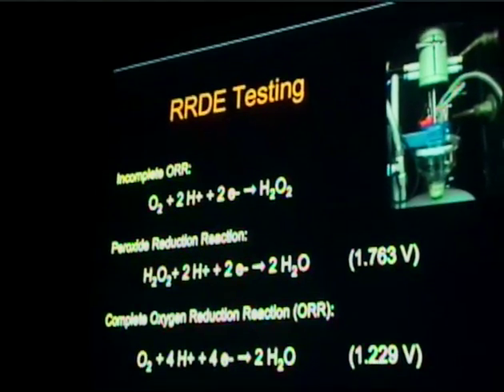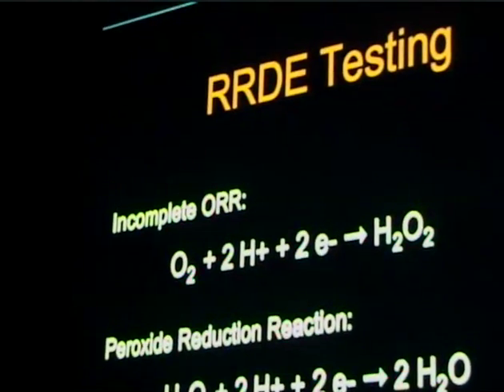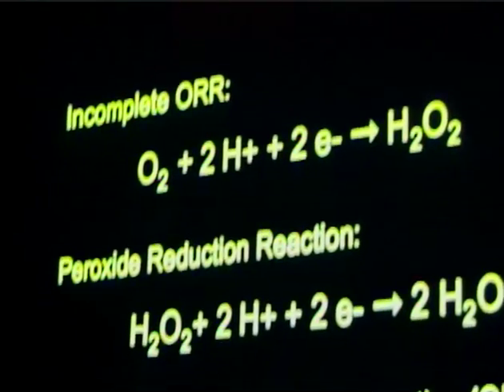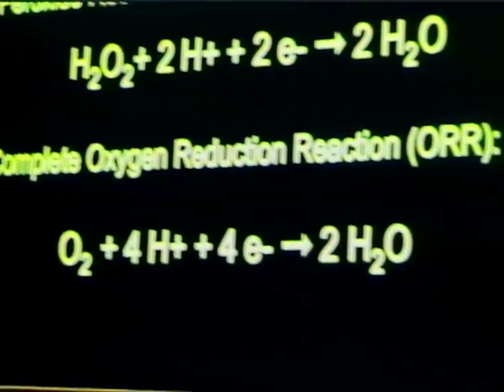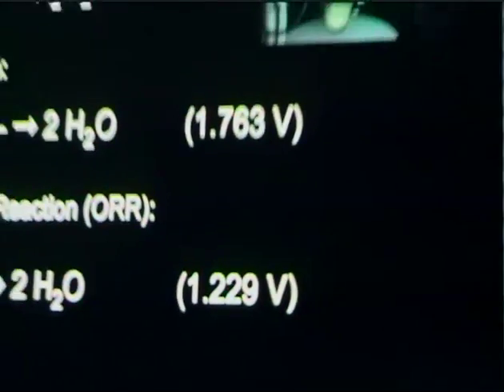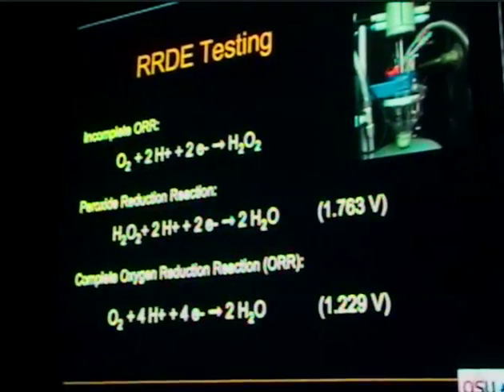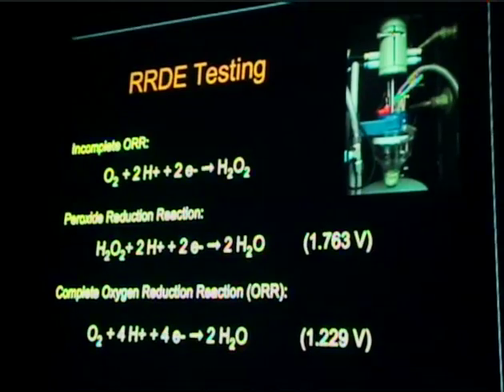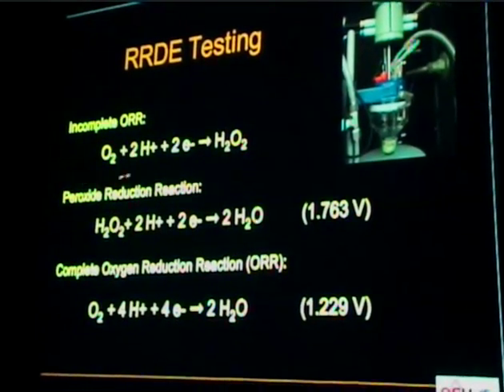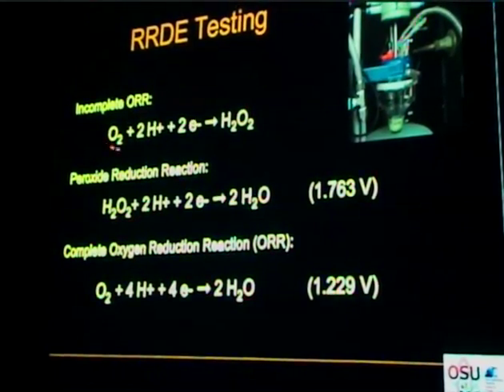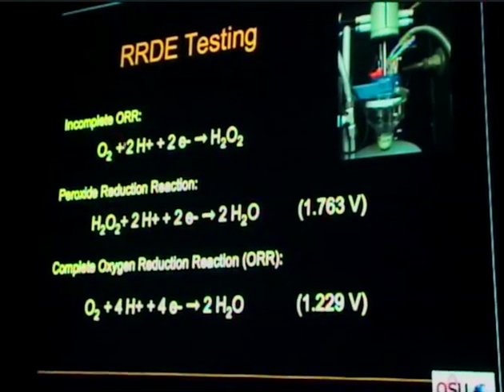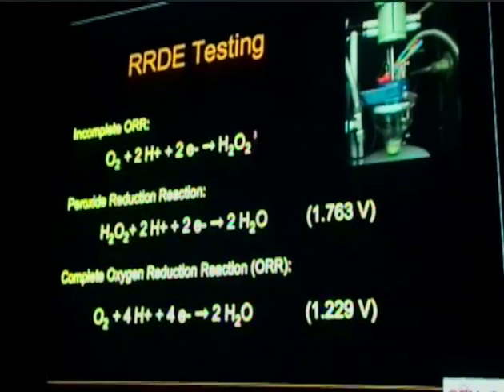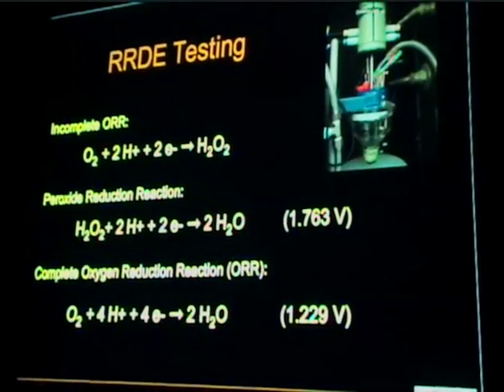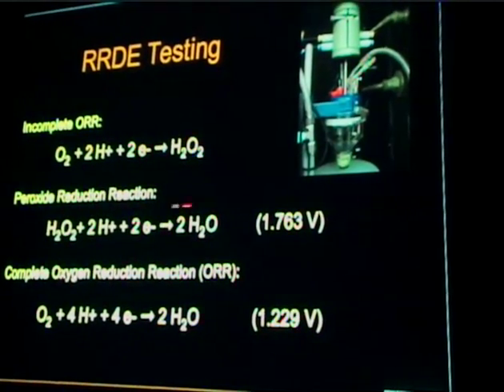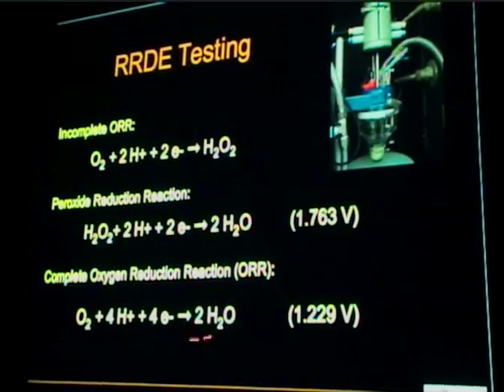Using a rotating ring disc electrode system, it is also possible to get the selectivity information in addition to the activity information, because if we look at the reaction that the oxygen can go through, there are really two possibilities. One is the incomplete oxygen reduction, giving hydrogen peroxide, which really gives us a net electron loss, and then the complete oxygen reduction, which is what we want.